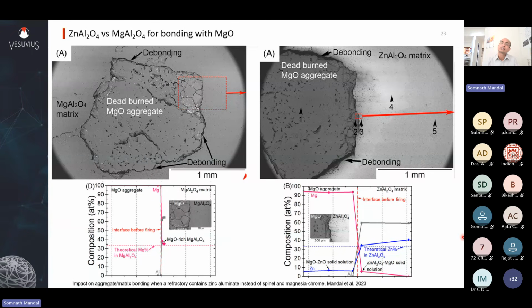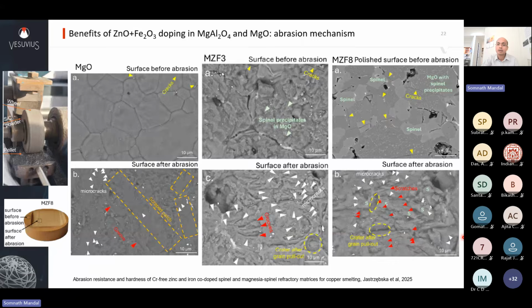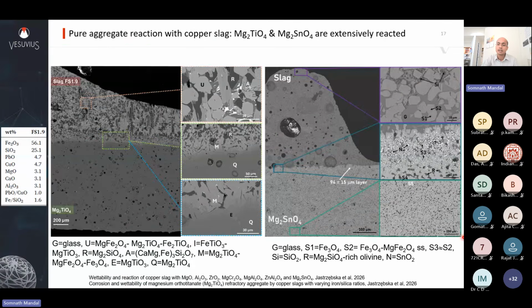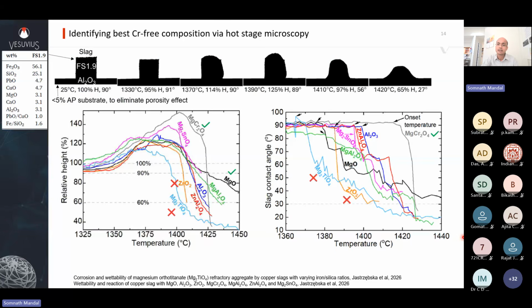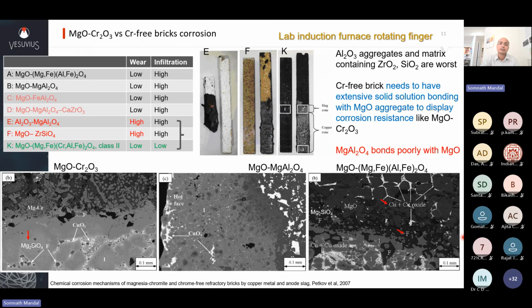Induction furnace tests, where you have bars of refractories dipped in your melt, which has copper matte on the bottom or pure copper on the bottom, and you have slag on top. These are commonly done in the industry. Currently, this magnesia aggregate based refractory with zinc aluminate or zinc aluminate with spinel matrix is ongoing. So this has not been done yet, but this is the way to do it. So for sure, this will be done. It's a matter of who does it fast.